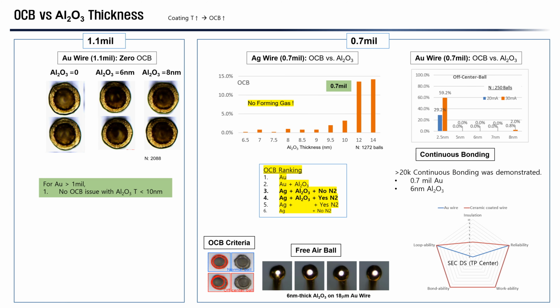On this slide, I'm going to show you the OCB sensitivity to the aluminum oxide thickness. The rule of thumb that we would like to propose is for the case of a gold wire, the diameter is greater than 1 mil. There's no OCB issue whatsoever with a 6 nanometer thick or 8 nanometer thick aluminum oxide coating.